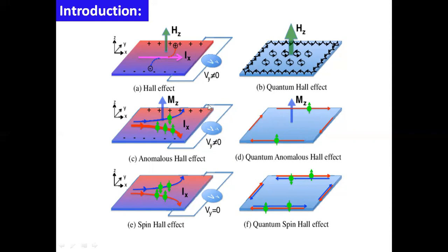So coming back to the quantum version of this Hall effect. Now, here you take the sandwich of two semiconductors. The interface between the two semiconductors will be a two-dimensional electron gas. And put that ultra clean interface under an extremely strong magnetic field at a very low temperature, and as a result of which you will end up with the quantum Hall effect, or precisely, it is also known as the integer quantum Hall effect. And it was discovered by von Klitzing in '80.